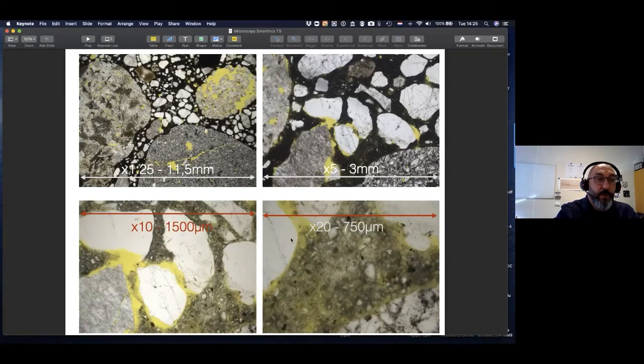So here you see another example. Again, under the polarized light microscope, you can observe not only very detailed features, but you can also look from far away. And when you do that, there are multiple advantages to it, of course. Then you can see the grain size distribution of your aggregates. You can even do point counting and have quantitative information. You can observe entrapped air. You see all these irregular entrapped air can easily be observed at very low magnifications.